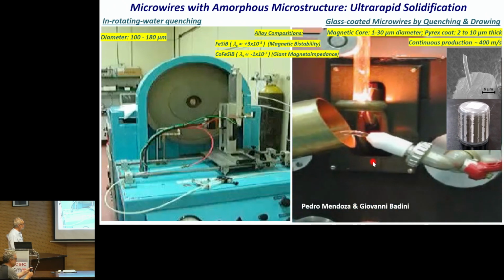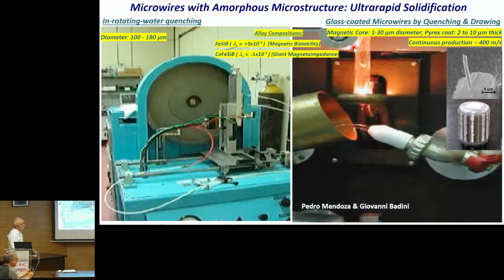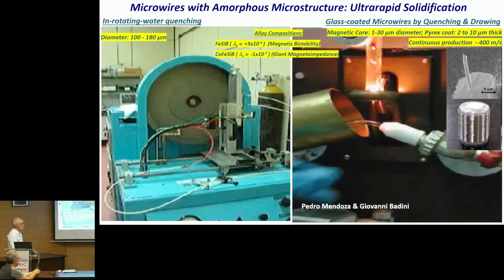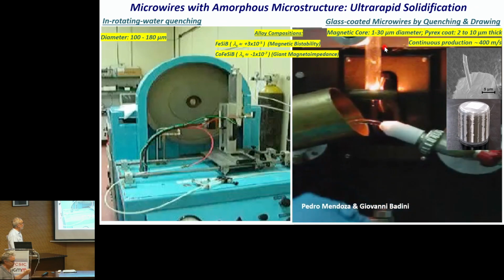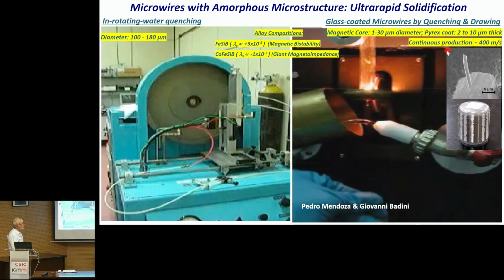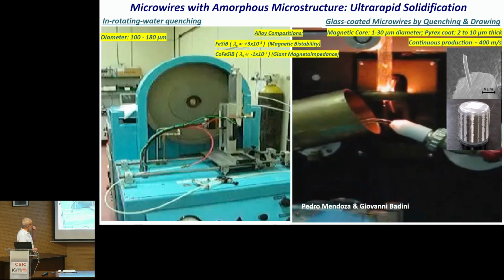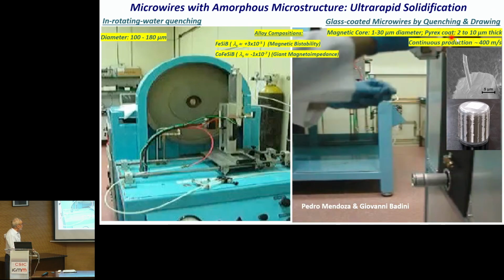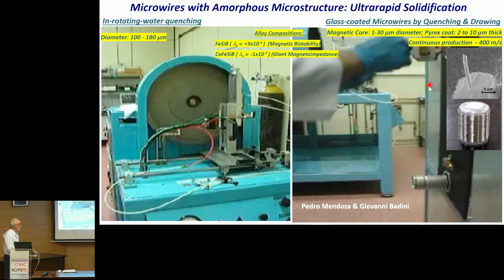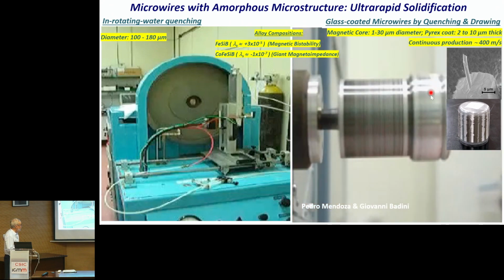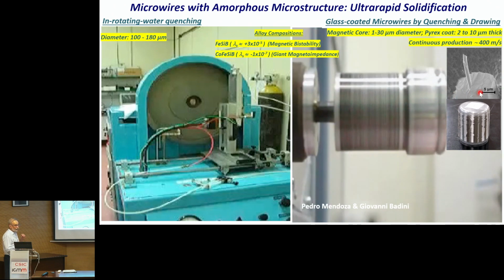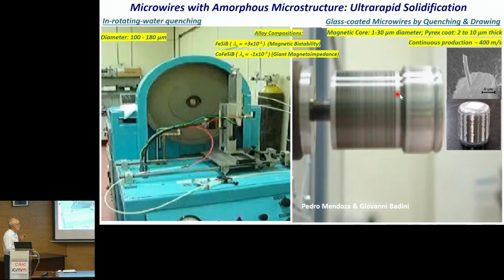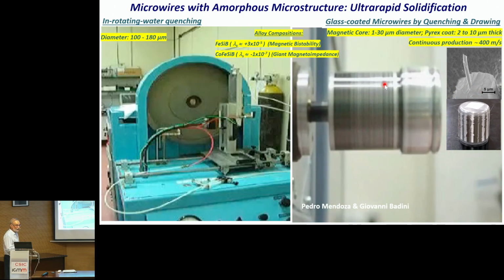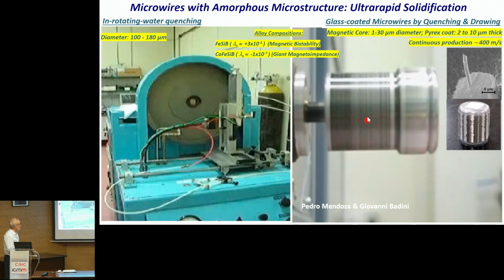Glass coated microwires. The magnetic core is in the order of from 1 to 30 microns in diameter, and they are coated by insulating Pyrex. It's a very manual process. It's very tricky, so not everybody can make that. In fact, it takes some time to get expertise in that.